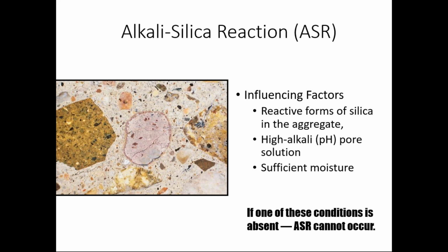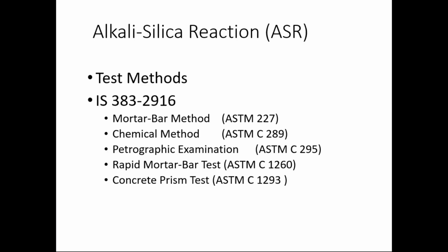One is high alkali pore solution, then how will it come? It may come through cement also. So cement containing alkalis and aggregate containing reactive silica, and the third one is sufficient moisture. So in the presence of these 3, only alkali silica reaction can take place. So IS 383 gives elaborate procedure for alkali silica reaction and marker bar methods. The mortar-bar method is also given in 383 as well as in ASTM standard. Chemical method is also given in ASTM as well as in IS 383.